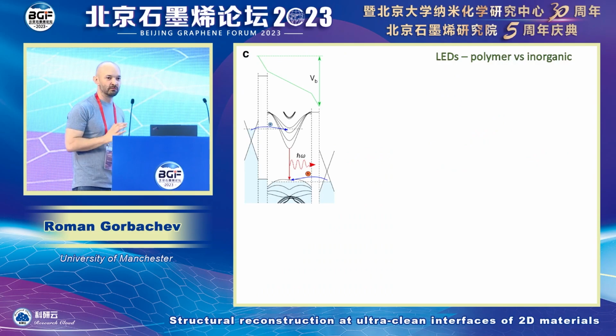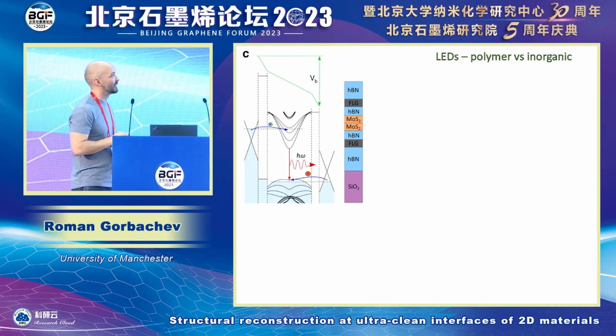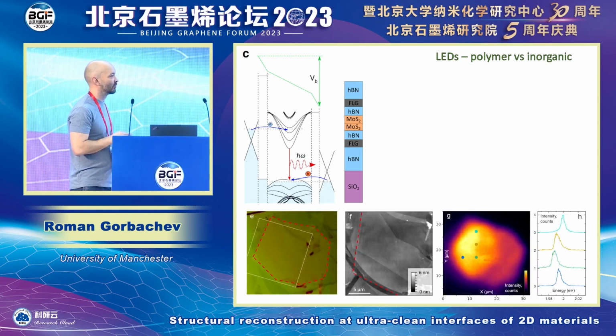But how about more tricky layer stacks? So here is a band diagram of a device which we called LED, light emitting device. And the basic principle is that you have a semiconductor like TMD in the middle, and then you have 2 graphene layers separated by tunneling barriers. You inject an electron from one graphene, a hole from another graphene, they recombine inside of the TMD and produce a photon. So this is basic electroluminescence. This is a layer sequence, so you can see this one is already 7-8 layers thick, a lot more complex.